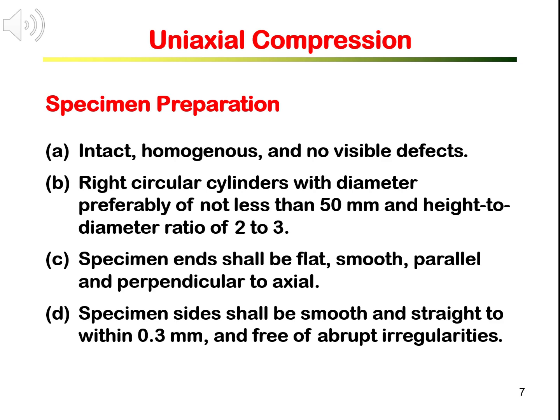Usually, specimens are cut from cores. Sometimes, a specimen can also be cored from a rock block. The specimen should be a right circular cylinder with a diameter preferably not less than 50 mm and a height to diameter ratio of 2 to 3. Rocks such as granite have minerals of coarse grains. The diameter should be at least 5 times the maximum grain size.